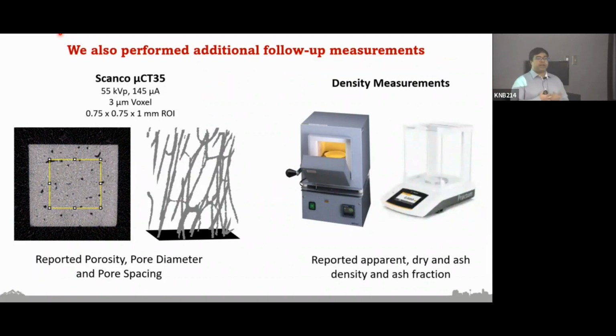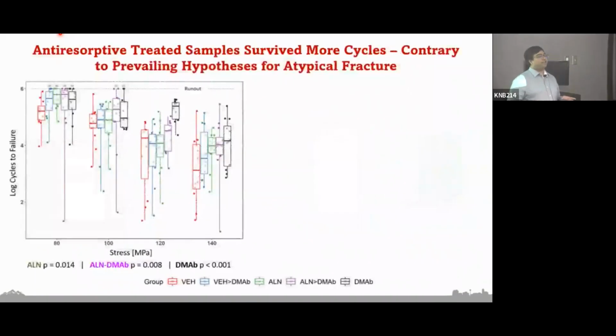We also looked at something called ash fraction, which we think is really indicative of composition of these tissues. So let me show you the results from all of that. And I think this was really cool and maybe surprising, depending on whether you believe my hypothesis or not. But in general, we did find that antiresorptive treated animals survived longer than the ones that did not.